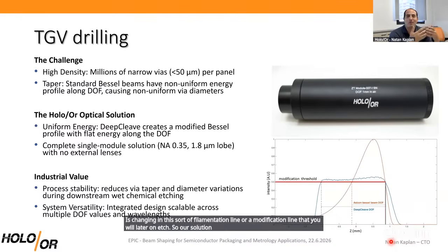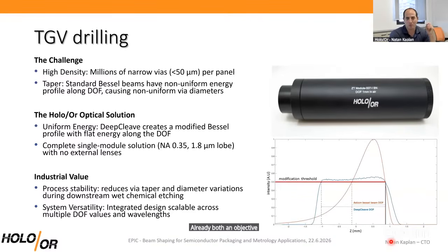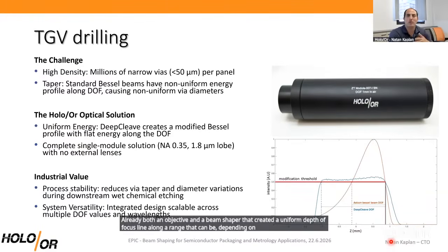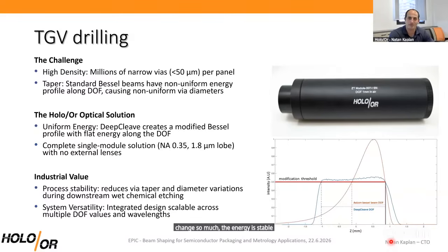So our solution for that in HoloOr is we produced the flat top in Z called the Deep Cleave, which is a family of modules that are basically both an objective and a beam shaper that creates a uniform depth of focus line along a range that can be, depending on the material you want to work on, from around 0.3 millimeter to 3 millimeter. They exist in various wavelengths from the IR down to green, and even now we have a new series in the UV. They are highly useful for through glass via processing, as they make the process much more stable because the diameter does not change so much. The energy is stable over the Z range.